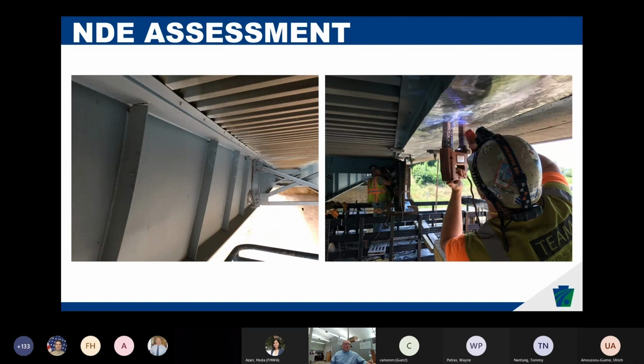So, but it was all contingent on there being no cracks in the top flange. Once all the work was done, you can see here that the transverse stiffeners were pulled out of the welds that connect to that top flange. So every one of those locations and every one of the locations where web to flange fillet weld was performed needed to be thoroughly inspected to ensure that there was no cracking in the top flange. They lucked out in this instance, and there was actually no cracking. So they were able to reuse that top flange.